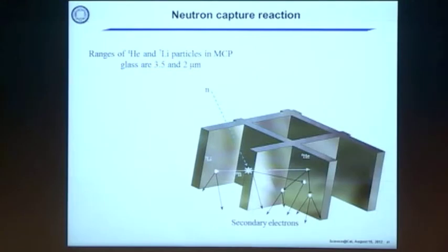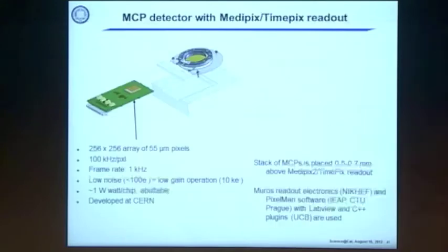There's a company we work with, Nova Scientific, who does these channel plates now. They changed the composition, added boron-10 into the glass. Now we are sensitive to neutrons. And in fact, we're very sensitive. We get an efficiency of 70% to cold neutrons, which is very unique for the neutron field. At the same time, the event happens just within the single pore. This pore, which is shown here, is again on a scale of a few micrometers, 10 micrometers. So the event stays within 10 microns. It doesn't go anywhere sideways like in a scintillator, where light spreads out.